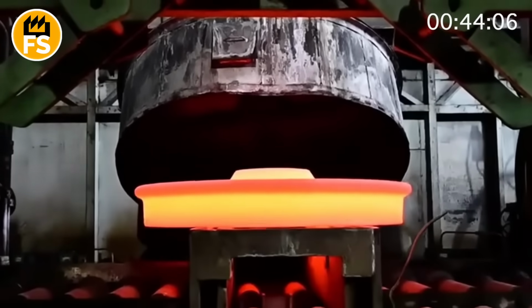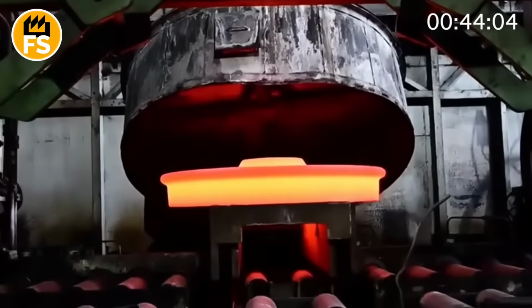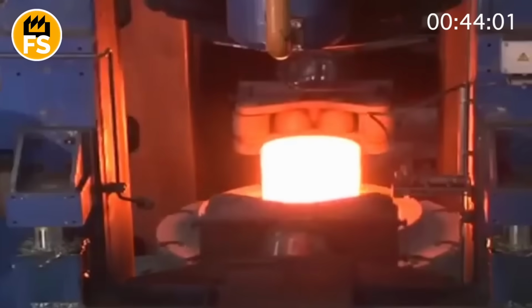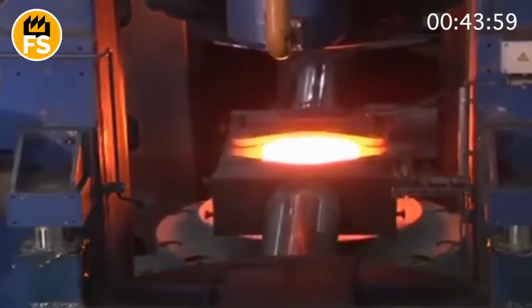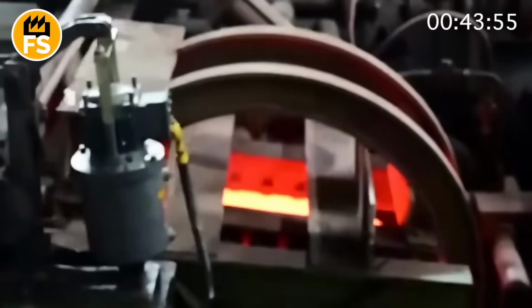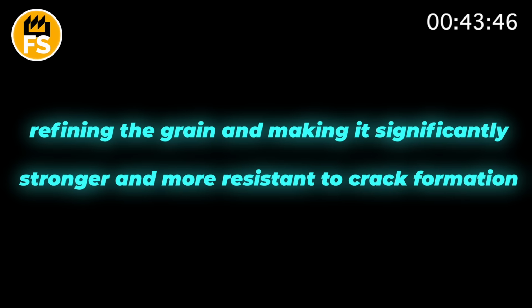Here it is clamped between several powerful rollers that with enormous pressure, roll and form the precise profile of the rim and flange. This process not only gives the wheel its final shape, but also works the metal's structure, refining the grain and making it significantly stronger and more resistant to crack formation.